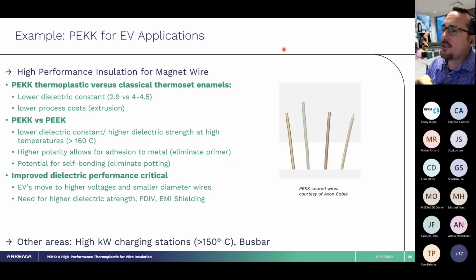We also have this unique benefit in terms of a potting material. Because we have control over the amorphous and semicrystalline behavior of PEKK, we can get layers to bond by taking them through anneal. So if you put two amorphous pieces of PEKK together, you can get adhesion by annealing them together as it crystallizes. This has really been beneficial for us in the world of 3D printing or powder coating, where you're building up layers to create your final part. This could be beneficial for potting in electrical applications as well.